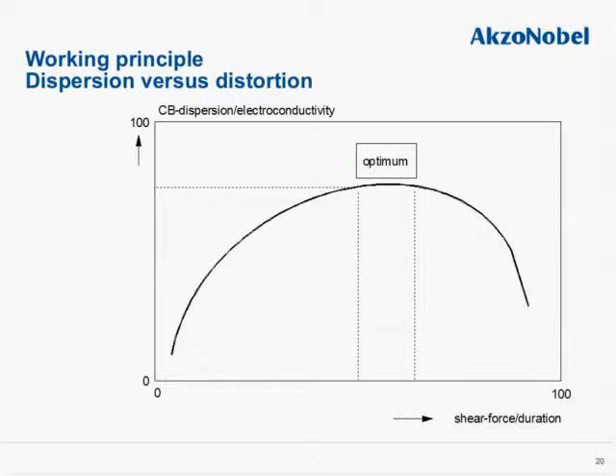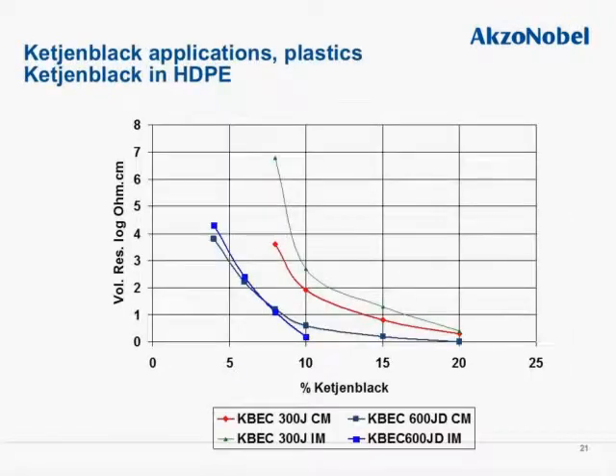In terms of mixing, ideally we recommend a twin screw extruder, but in essence, any internal mixer can ensure dispersion of Ketjenblack in a polymer matrix, at the same time using some processing aids if that's necessary. We don't recommend a single screw extruder. It will probably generate the least shear, and one pass through the extruder will probably not be sufficient to ensure a good dispersion of the Ketjenblack.